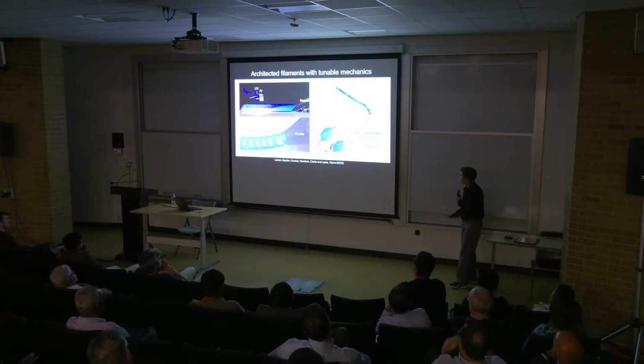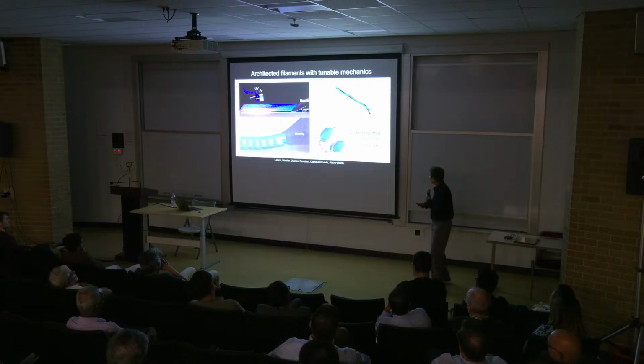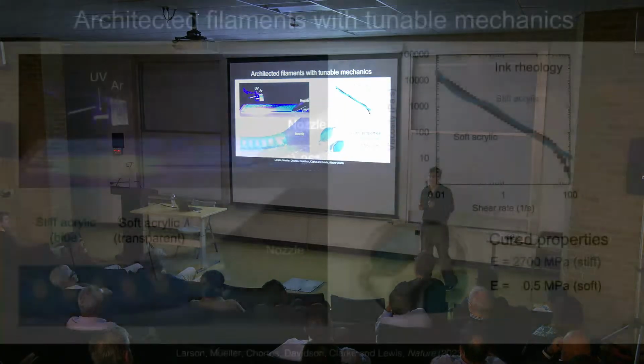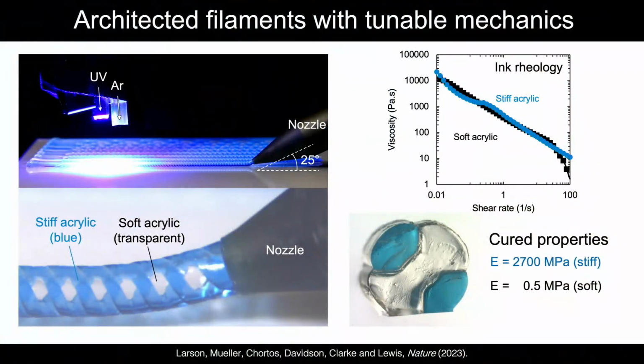There's a stiff and a soft acrylic material in the ink, in the co-flowed ink reservoirs. And these have nearly identical shear thinning responses and nearly identical shear yield stresses. And what's important, though, is once they've been UV cured, their stiffnesses vary considerably, right? So we've got about a 5,000x difference in the Young's modulus of the stiff and soft filamentary features inside each of these given filaments. And this is just one cross-section that shows the blue, the stiff, and the soft material.